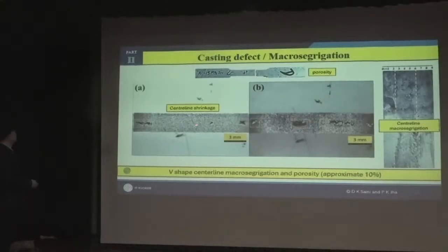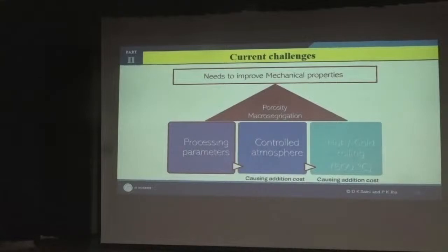You are getting some centerline shrinkage, and certainly you must have a good idea about the shrinkage which you get. Normally it is towards the center because of the solidification pattern, which moves from the sides and goes inside. So your shrinkage normally you will be getting mostly towards the center line.